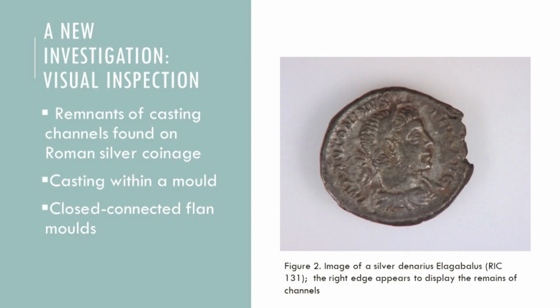So before sectioning the coins, I completed a visual inspection and identified that remnants of casting channels called sprues were on some of the coins. This indicated that the flans were cast in a mould, and the presence of casting sprues also points towards the mould typology, which would have been one with individual depressions, each connected by channels that would distribute the molten